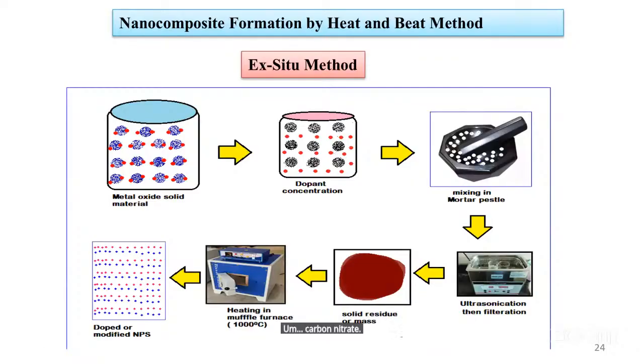For example, you have to dope carbon nitride into Fe2O3. So you take this Fe2O3 and this carbon nitride. You mix this thoroughly in a mortar and pestle for 1 to 2 hours, continuing mixing. After homogeneous mixing, you simply subject this mixed phase to the ultrasonic bath for at least 1 to 2 hours continuously. After ultrasonication, you have to filter this material and dry the precipitate. Subject this precipitate to heating in a furnace beyond 800 degrees Celsius for 5 to 6 hours. And finally, you'll get the modified doped metal oxide or nanocomposite form.